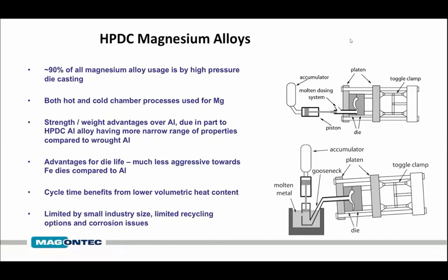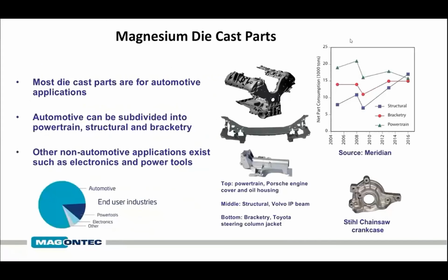Also, magnesium has an advantage over aluminium because it's much less aggressive towards steels, so you get much longer die life. The heat that you need to remove is less, so the cycle times are better. The main limitation is really the industry size. There is less experience using magnesium and limited recycling.